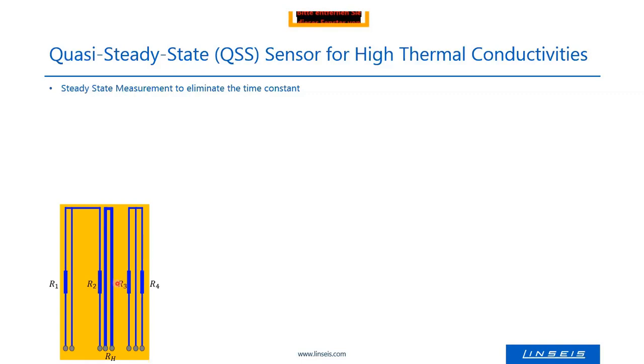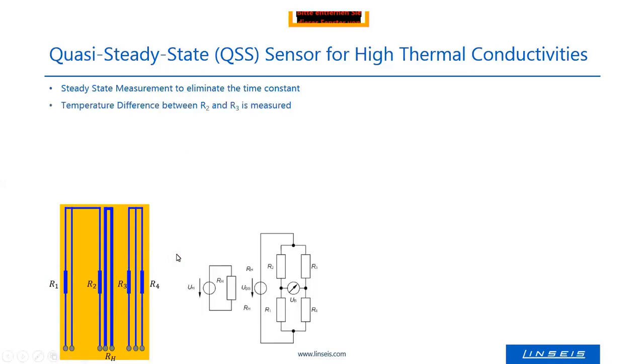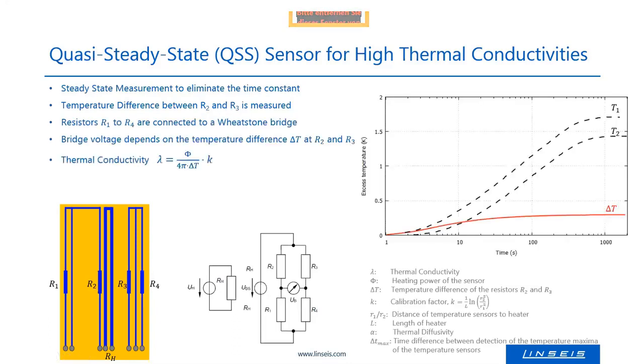And we measure until we have a constant delta T between R2 and R3. So it is a steady state method, because we apply a heating current and then we measure until we have a constant delta T, a constant gradient. The resistances or thermometers R1 and R4 are needed to build the Wheatstone bridge in the sensor, as we see here.